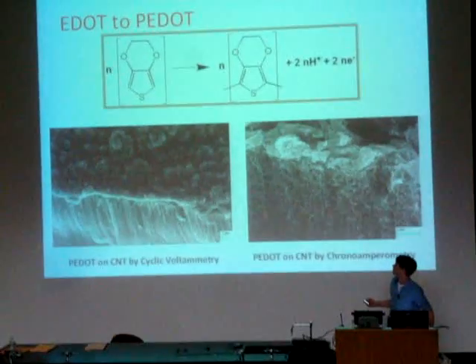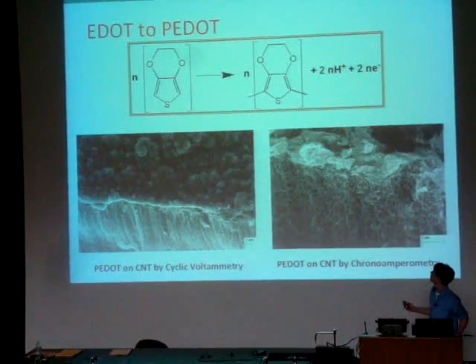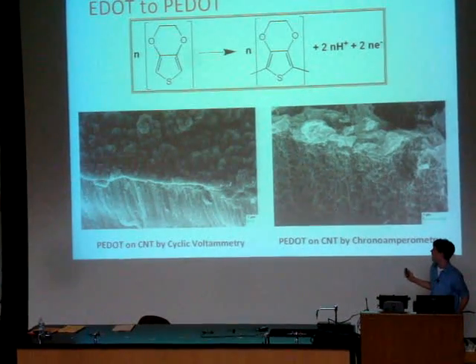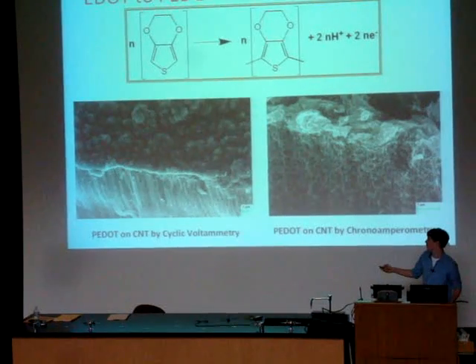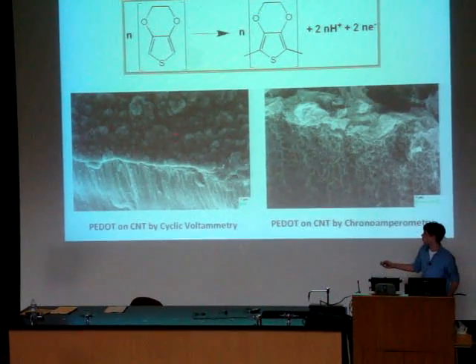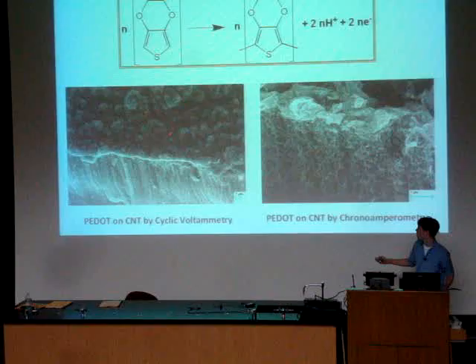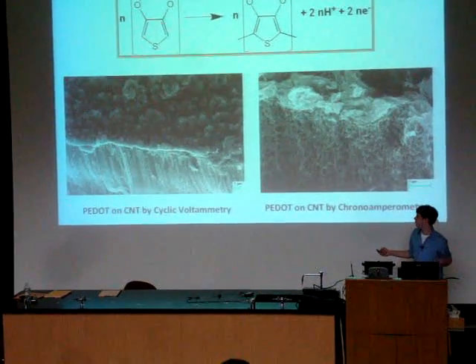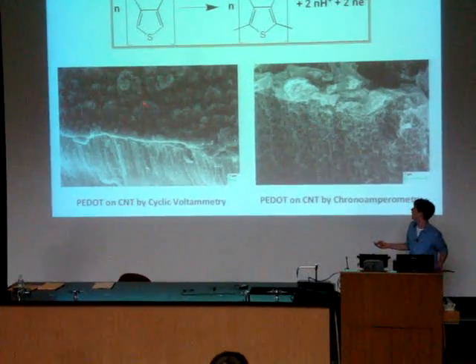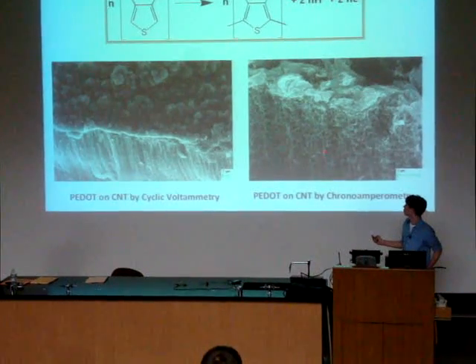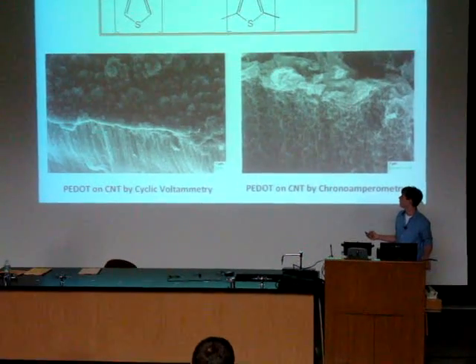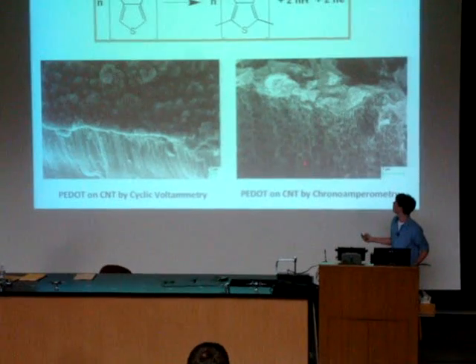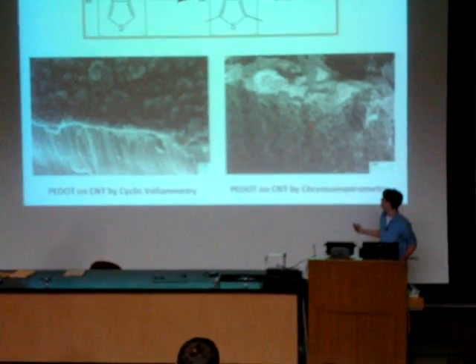Over here, this is the after polymerization. This is the chemical equation of the polymerization. And over here depicts the cyclic voltammetry results. As you can see, the PEDOT is sort of accumulating on top of the carbon nanotubes rather than coating them. It's sort of just clumping on top. However, the chronoamperometric results created a more desirable and porous polymer, which coats along the nanotubes. So we use these when fabricating the coin cells instead.